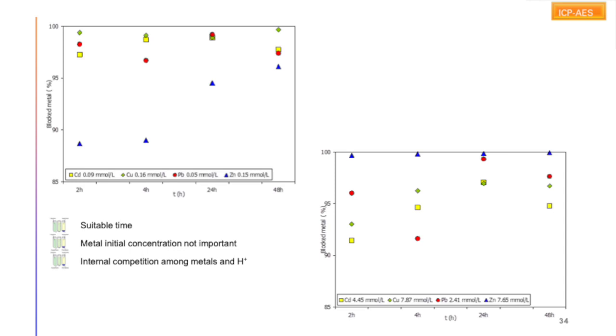Then we analyzed all the supernatants with the ICP-OES, and in this case, we plotted time against the amount of the metals that can be immobilized. So we can say that 24 hours is the suitable time, and it doesn't matter the initial concentration of the metals, but it's important to understand that only for zinc we observe a different behavior, because increasing the concentration, zinc is better immobilized, and we can explain this particular behavior with what we call the internal competition. So it means metals can compete among themselves and with the hydrogen ions to reach the site to be sorbed over the surface of the phosphate, and this is important to remember.